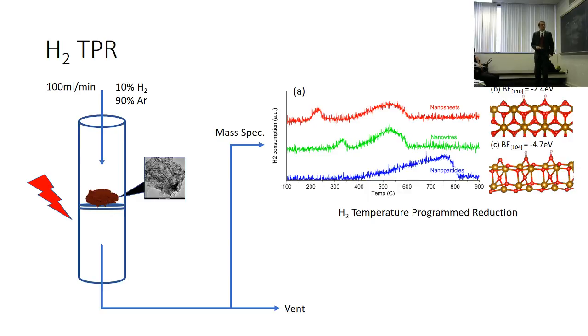When you heat these structures up in hydrogen, you find that the nanosheets and the nanowires are pretty similar. They have the same peak over here, but they have this earlier peak, and the nanoparticles take off later. Remember what we said in the last project: if you react at a lower temperature, you're more reactive; higher temperature, you're less reactive.